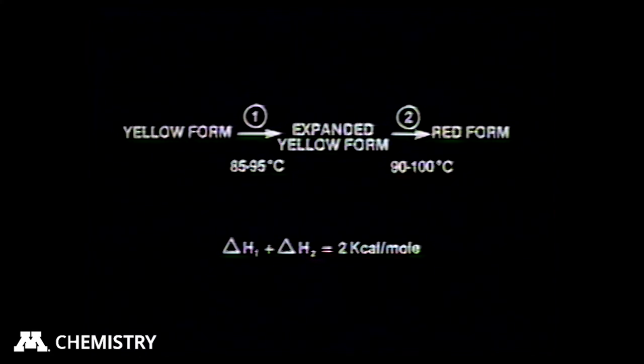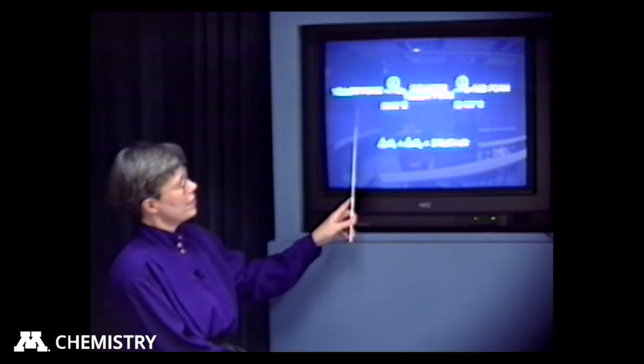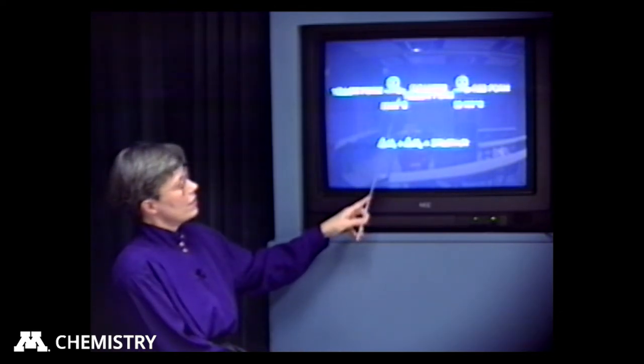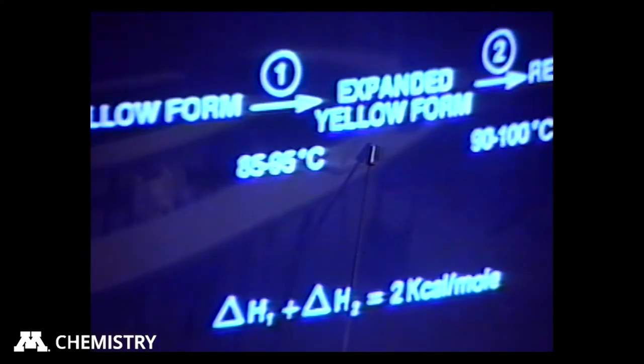And I also didn't tell anybody about it. And what I observed after that was that they turned red. And so I thought, I've observed this yellow to red transformation, and what happened in the meantime is just beyond me, and I will just forget about it. And so we decided to videotape this transformation. And in doing so, we still didn't see this other unusual step. But I'm going to show you a videotape in a minute here where you will see that what happens is the yellow form changes to an expanded form, and it actually pops.